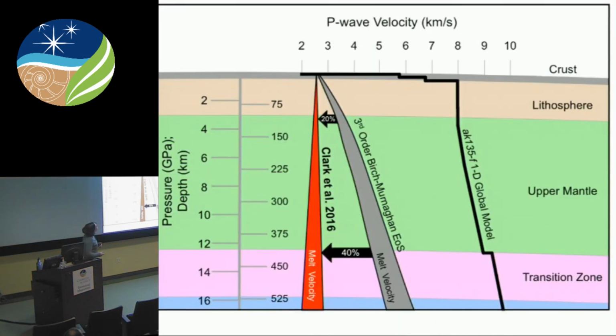When we do that, we get significantly lower velocities as a function of pressure than has commonly been modeled in the literature. Here we have P-wave velocity as a function of depth. Here's our 1D global average model. Here's using a crystalline equation of state and the 1 atmosphere properties to predict melt velocities. And here's using our very weak pressure dependence. We're talking about a 20% lower velocity at the LAB and nearly a factor of 2 at the transition zone for melts if we use our model based on network flexibility densification rather than crystalline equations of state.